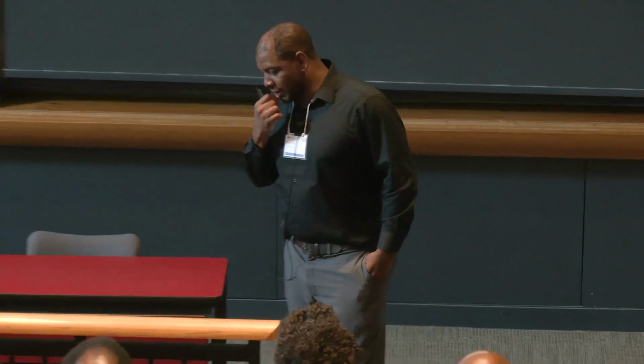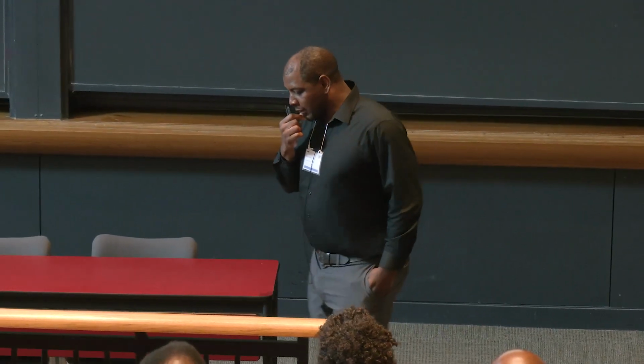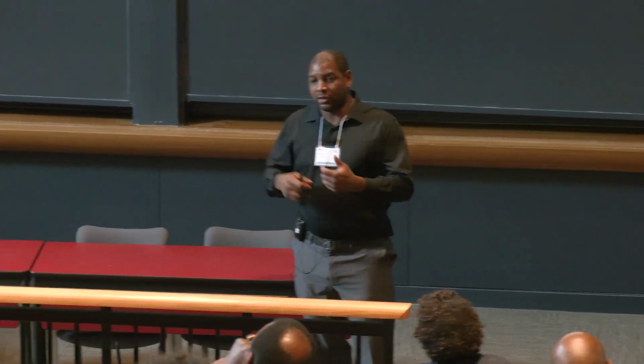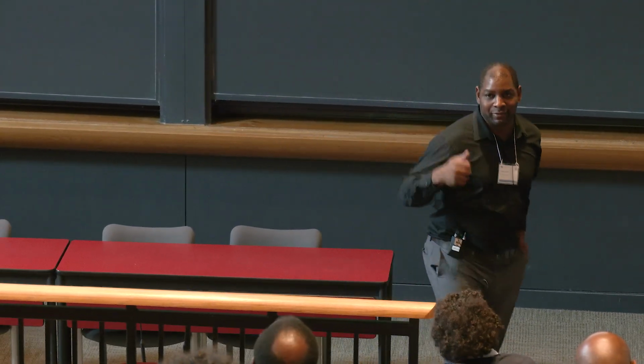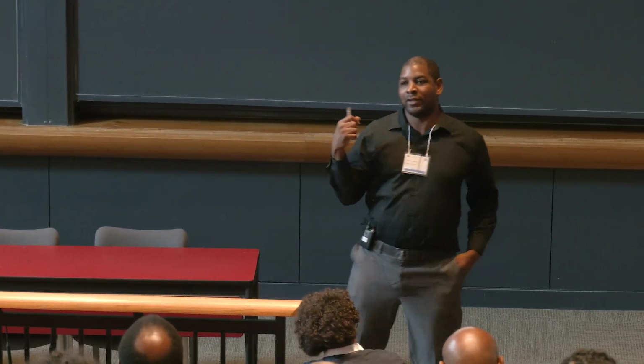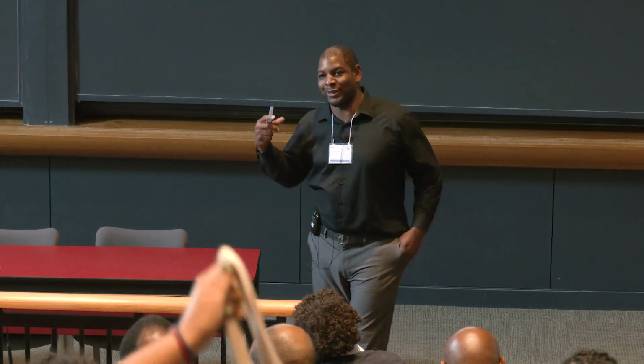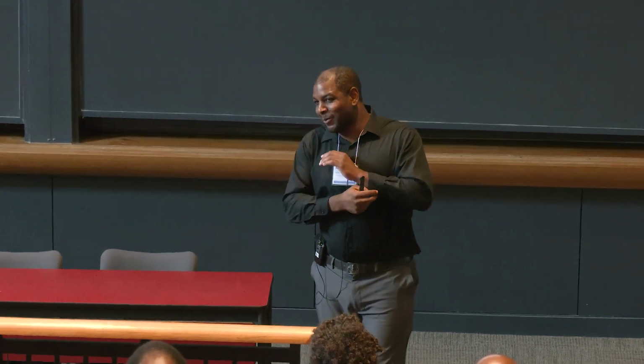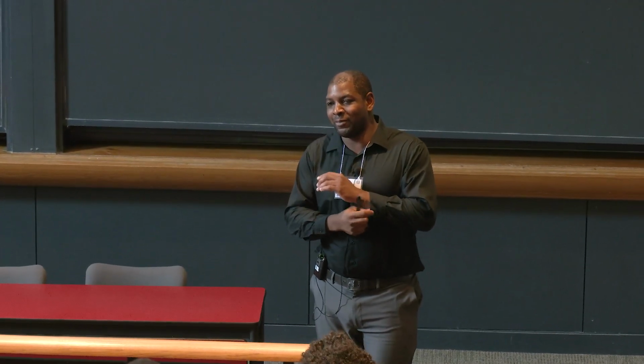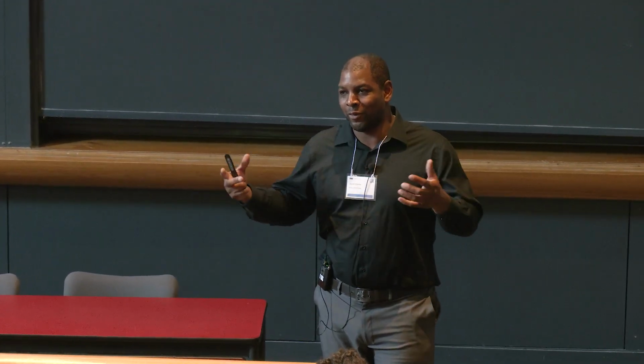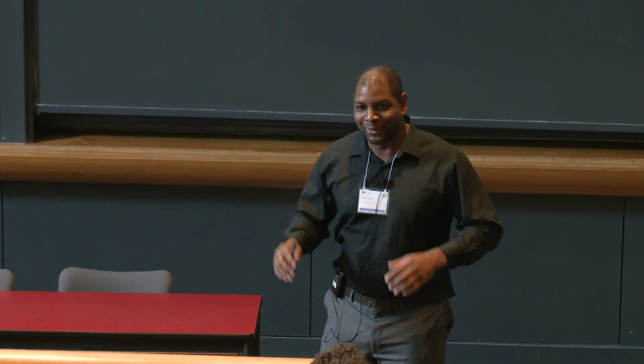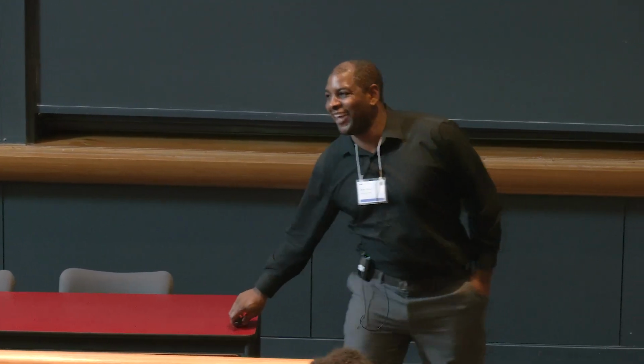Oh, yeah, for strain, yes, that's a very interesting case. I mean, with strain, you can change the size of your DMI. And of course, strain happens in a lot of these systems. I just kind of left it out. Actually, how you would stabilize these systems has not really been developed experimentally. I'm discussing with a friend, but you would have to grow them under strain and then remove the strain so they would relax back, which is not a simple feat.